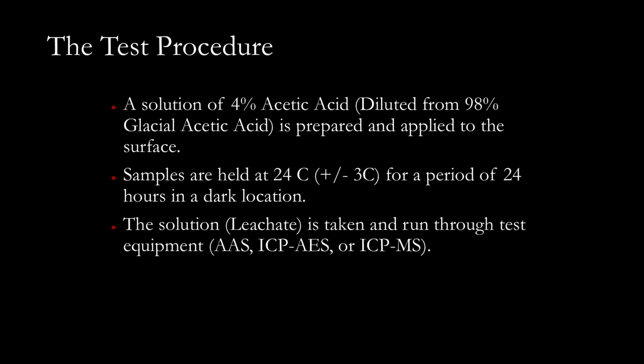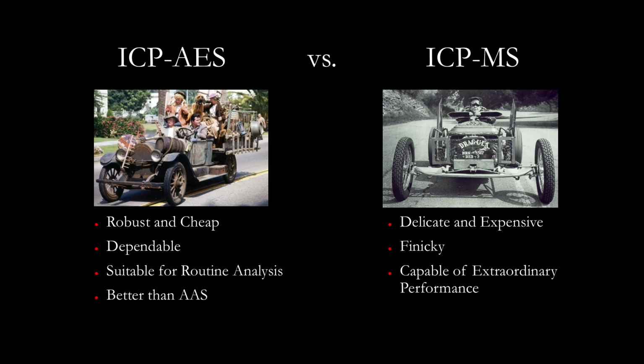We can then take that solution, the leachate, and run it through these test processes to actually count how much of what came out. And this is where things will get fun. We'll talk a little bit about ICP AES and ICP MS. ICP AES is inductively coupled plasma with atomic emission spectrometry. We'll just go with that. Essentially, you're taking a flame, creating it in a magnetic field to create a plasma, which is burning at ridiculously hot temperatures, vaporizing most of what's in that leachate solution, and then the AES portion, the atomic emission spectrometry, can count the amount of atoms, the ions, the copper ions that are floating around. It's robust, it's cheap, it's dependable, it's kind of suitable for routine analysis, but it's not the most precise.